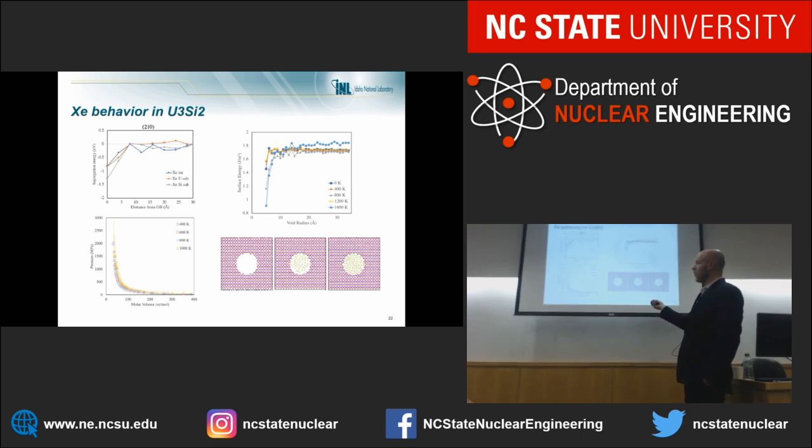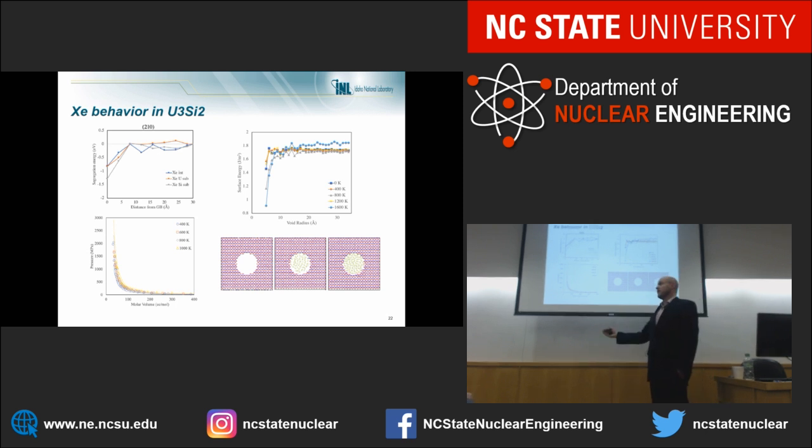Whenever the molar volume is very, very low, it approximates a van der Waals gas, but whenever we're at fairly high pressures in these systems, there's a significant amount of variance compared to just modeling the xenon as a van der Waals gas. These are realistic pressures for smaller bubbles in these systems, such that we need to account for the different equation of state for xenon in order to get the actual bubble evolution whenever the bubbles are small.